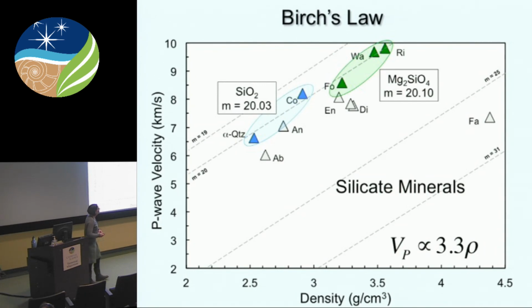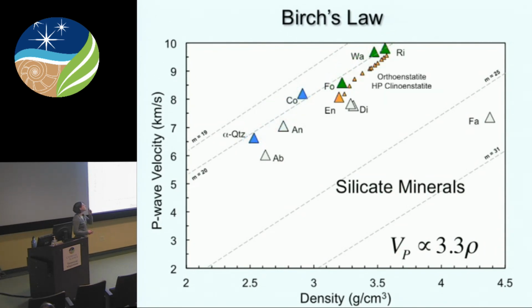All right, so let's look at silicate melts. Oh, actually, we're going to talk about crystalline silicates for just a second more. So we can also see that this relationship holds when you change density by increasing pressure in a single phase. And that's what's shown here for enstatite as it goes through the ortho-enstatite to clino-enstatite phase transition.